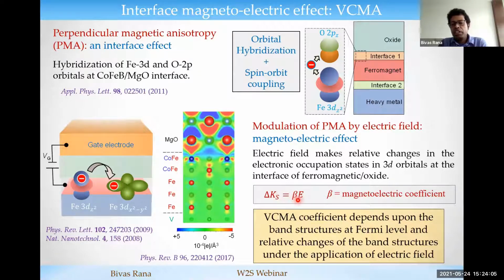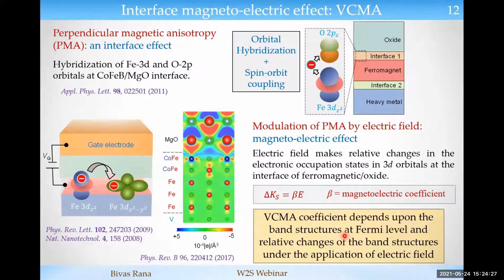Anyway, this change of the anisotropy can be written in a simplified manner. It can be written as linearly proportional to the electric field. That is one of the advantages of this voltage control magnetic anisotropy. But this is not the case for all heterostructures, because this voltage control magnetic anisotropy coefficient always depends upon the band structure at the Fermi level, and how the relative changes in the band structure occur under the application of electric field.